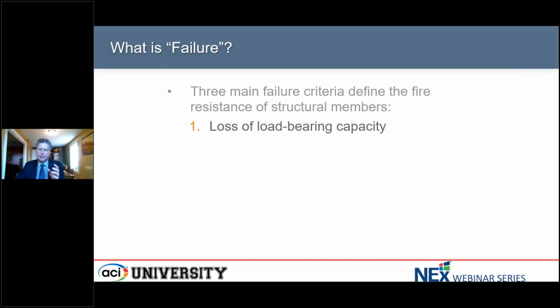So the first one is the loss of the load-bearing capacity. If you're testing a slab and you have load applied to it during the fire exposure, if it falls into the furnace, then the test is over and it's failed. So I think that's fairly obvious. The second one is that you have the loss of the fire separation characteristics. And that's really the same situation I talked about, the slab on the furnace and you're heating from below. If the top surface gets too hot, then that might spread the fire onto the next floor. So that's the next consideration.